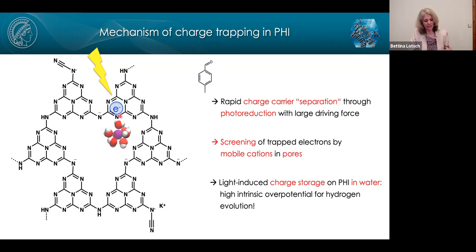And that tells us that intrinsically, these carbon nitrides are really bad hydrogen evolution photocatalysts. They have a high intrinsic overpotential for the hydrogen evolution. And apparently they only become good hydrogen evolution catalysts if we add a co-catalyst. So that is something we need to keep in mind. Carbon nitrides as such are quite bad hydrogen evolution catalysts, but that is something we can take advantage of. And I'll come back to that in a second.